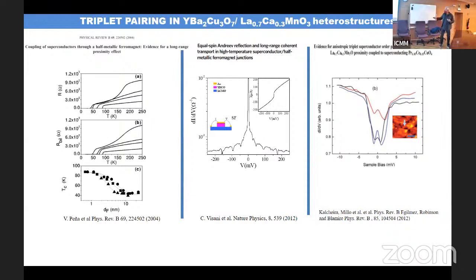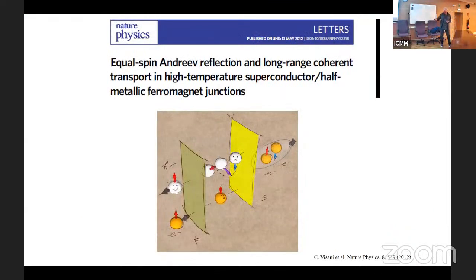Also, Yoav Kalcheim in Oded Millo's group in Israel were able to measure a superconducting gap on top of the ferromagnet in bilayers made of YBCO and manganite. So we were convinced that these triplets actually were generated at these interfaces. And that's the reason why we really decided to pursue this Josephson program, right?